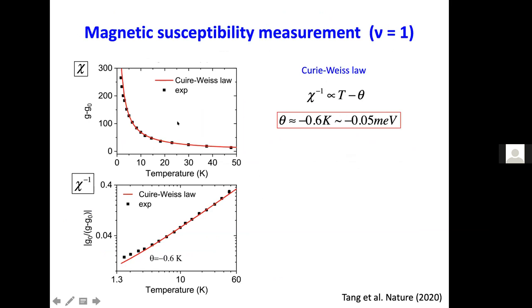indeed follows some kind of Curie-Weiss law, and this is for nu equals 1. The analysis tells us that the Curie-Weiss temperature is on the order of half a Kelvin.